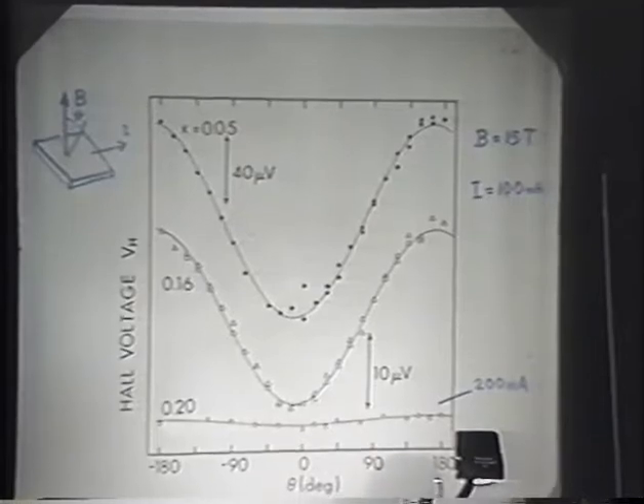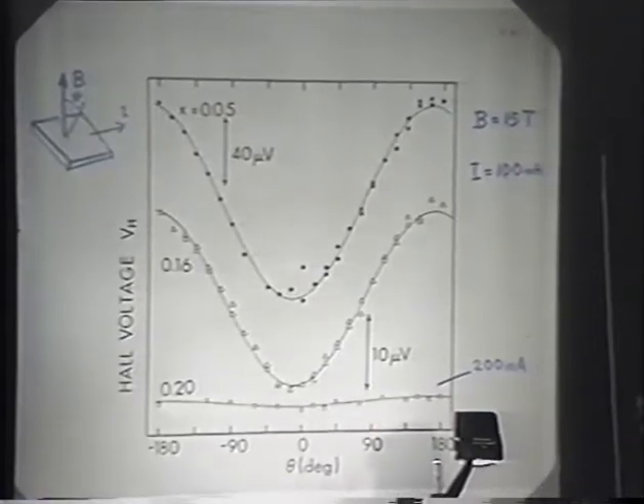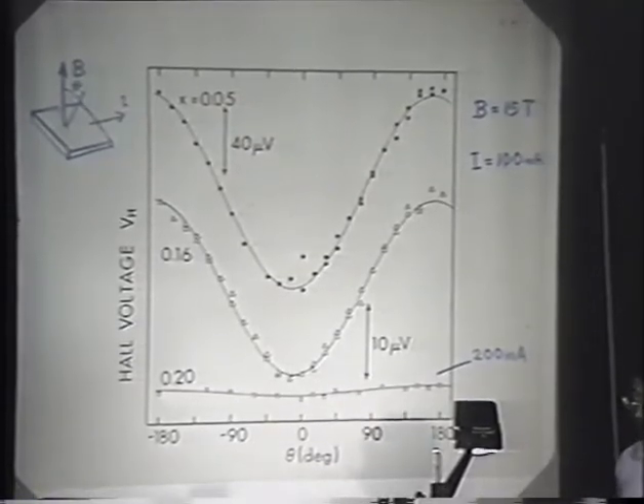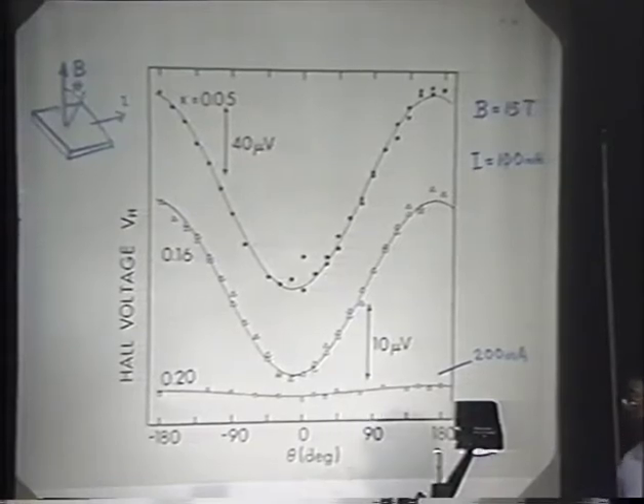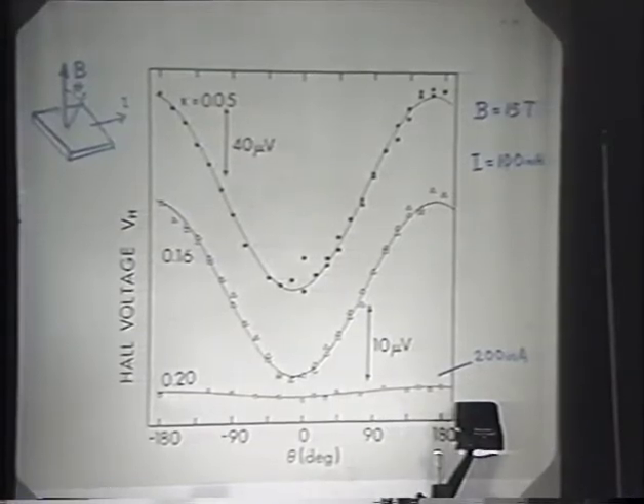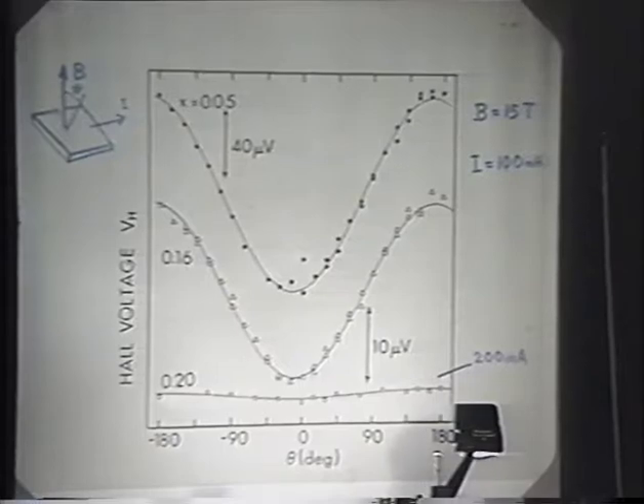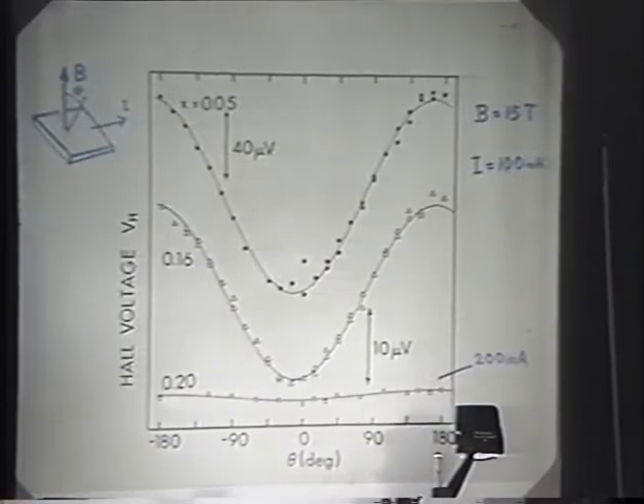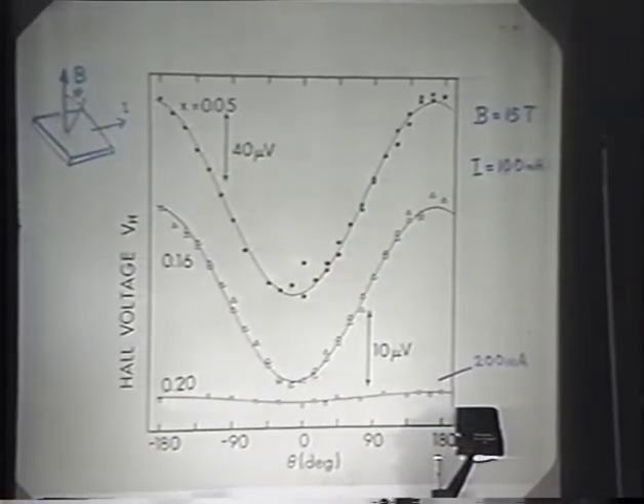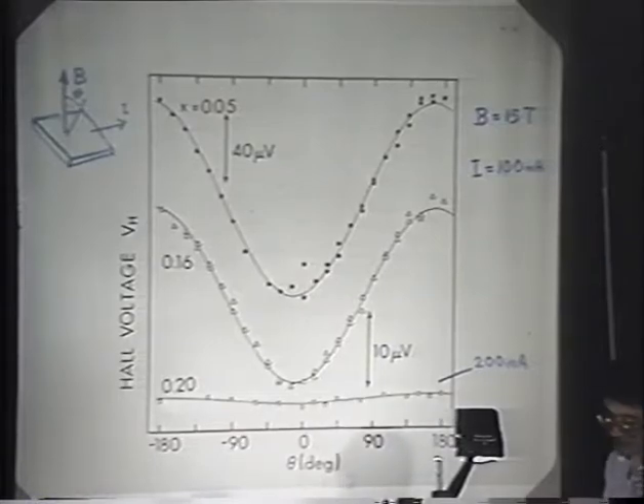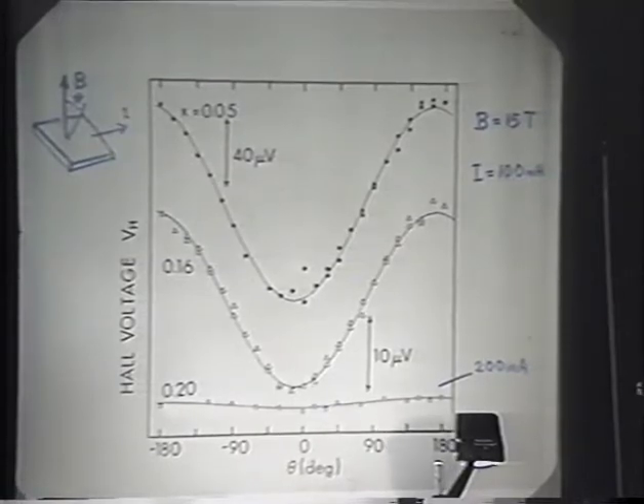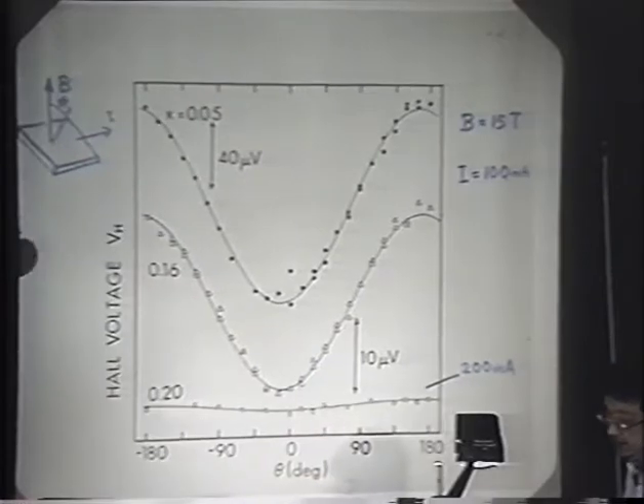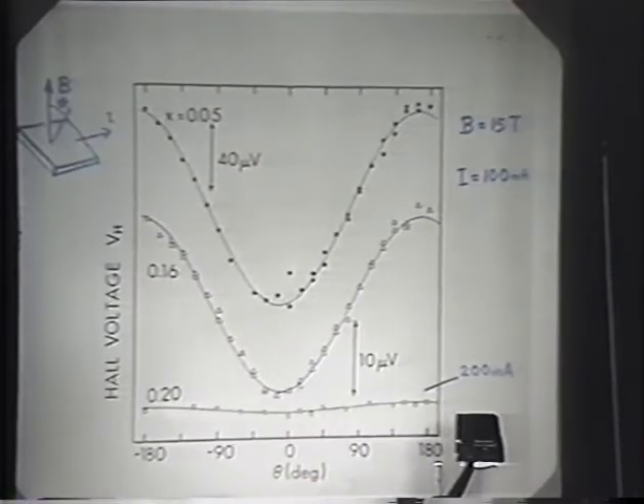The signal is small depending on x. For x of interest near 0.15, 0.16, the Hall signal turns out to be 10 times smaller, or 30 times smaller actually, than what you would expect from counting 1 carrier per strontium. We measured this at the magnet lab by rotating the sample in a superconducting field at 15 Tesla. And subsequently, also did it in a Bitter magnet, although it's much more noisy when the field is running.